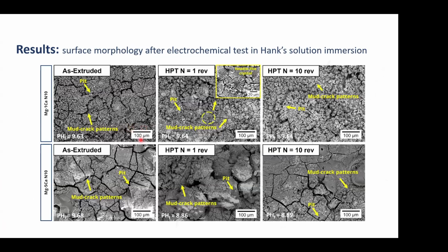We check the surface morphology, and we see along the fine grains the corrosion carrying out, pitting corrosion, and what's called the mud crack patterns. And what we can get from this is that the corrosion degradation proceeds rather homogeneously along grain boundaries. So the smaller the grain size, we see that it's improving the biodegradability behavior.